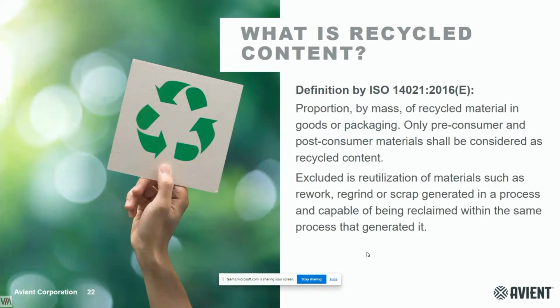By definition, by this ISO norm, 14021, the regrind and the scrap generated within the transformation process are excluded. I mean, if one extruder or injector is recovering material and parts, they regrind it and they use it again in a certain percentage in order to continue producing parts, that is out of the definition of recycled content. That is a common sustainable practice in a traditional injector or extruder if the quality of the final part allows it. But we cannot consider this as recycled. We can only consider as recycled, after this ISO norm, the pre-consumer materials and the post-consumer materials.